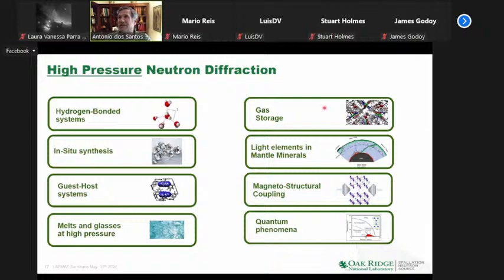There was gas storage for the hydrogen economy, and more relevant for us, the direct magnetostructural coupling, like as you change the structure, how is the magnetism changing? And also, of course, quantum phenomena, where you can really stay at very low temperatures and basically use neutrons to interrogate both these magnetic phases and these superconducting phases. And in this case, it is a uranium germanium compound, where any other technique not only would warm it up, but basically uranium would dominate the signal. And here you can truly see how the whole structure is behaving.